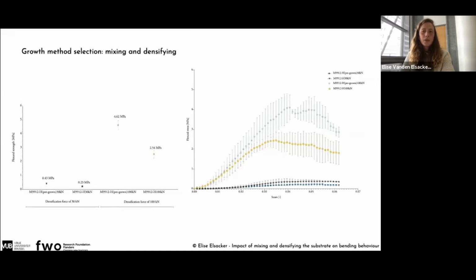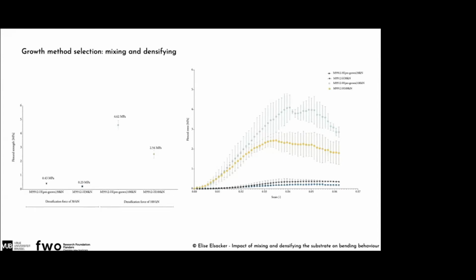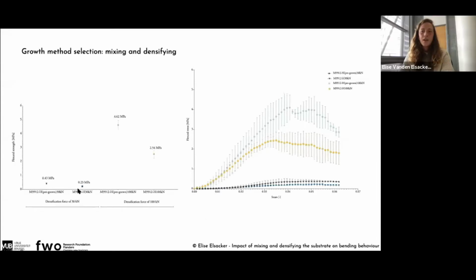So the first purpose was to understand whether pre-growing and mixing the material during the growth of the organism would impact the mechanical properties. The idea here was that the substrate, pre-grown in bags, would stimulate a more high-flow robustness, because we could knead it and massage it. That would also allow more airflow within the substrate. On the other hand, if you grow the substrate directly in the boxes, the density would also enhance, because you can compress the fibers more densely. So those two things were tested here.